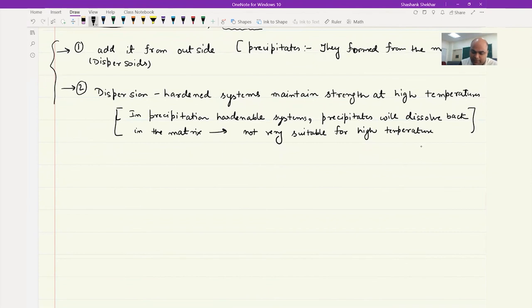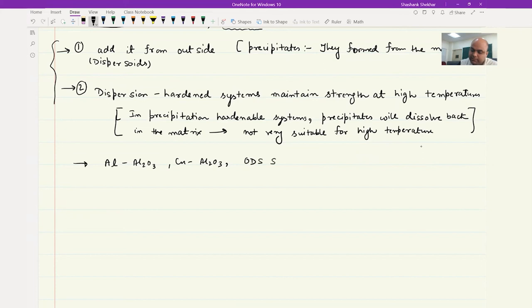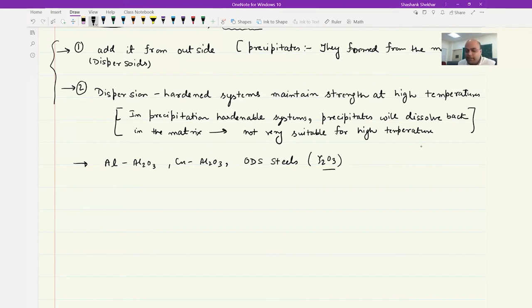What are the examples for dispersion hardened systems? You have aluminum with Al2O3, or copper with Al2O3. One of the famous examples is ODS steels — Oxide Dispersion Strengthened steels — which are being used in nuclear power plants. These are ferritic steels with high chromium, and you add yttria, Y2O3, as a dispersoid in the matrix, which provides strength at higher temperature.